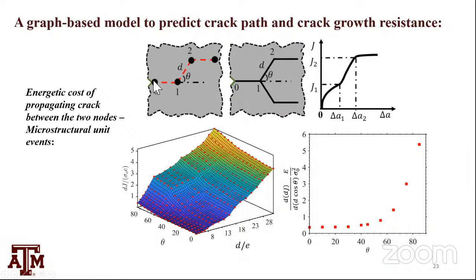And so if I grow a crack from 0 to 1, I have an increment, a jump in J, right? That goes from 0 to 1. In this case, 1 to 2 shown here, right? So I get a 1 to 2 jump. This 1 to 2 jump is basically what we're getting here in this case. And we add when I go from 2 to 3, 3 to 4, 4 to 5. I'm not running the crack all the way to 3; my unit event is always this, and I'm only changing D and theta. So the plastic dissipation is also in a way incremental form, and that tends to capture the addition of the plastic increment as well.